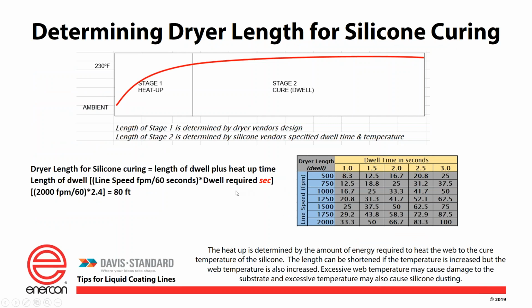In silicone, what you're looking at for a dryer is you need to heat the silicone up to a temperature, and you need to maintain that temperature for a period of time. So that's your dwell length. Now, those numbers will be given to you by your silicone vendors for each product. If it's water-based or solvent-based, stage one is not only heat up, but it's the evaporation. We get rid of that. But most silicones today are going to be 100% solids in this talk. So we heat it up, let's say 230 degrees Fahrenheit, and we keep it at that for a dwell time.